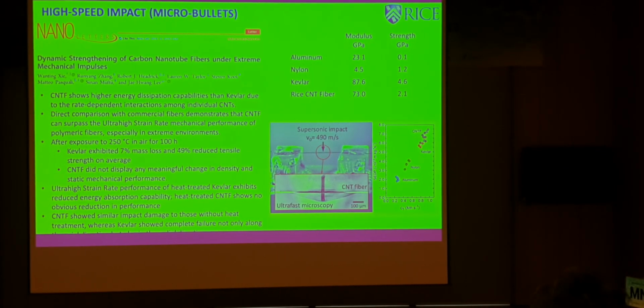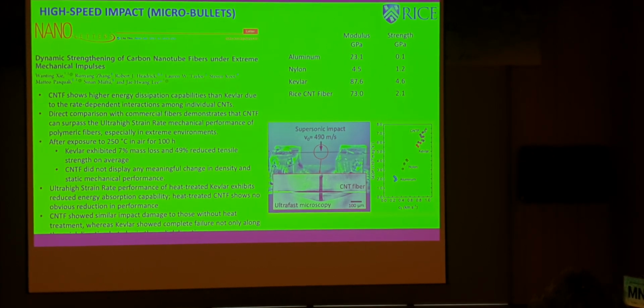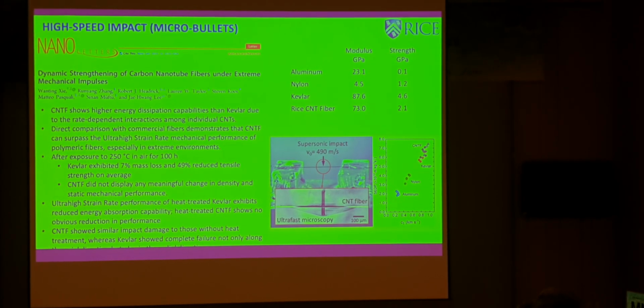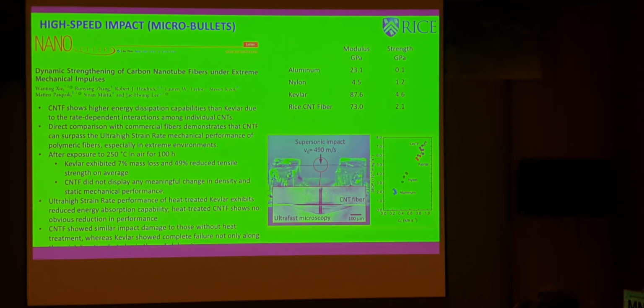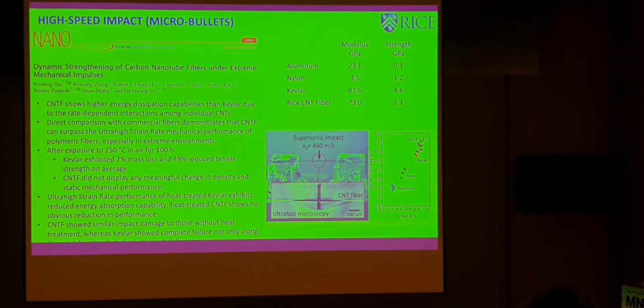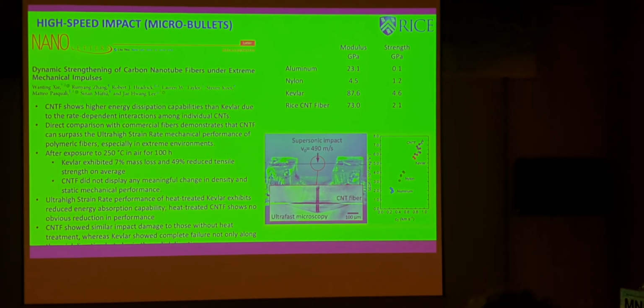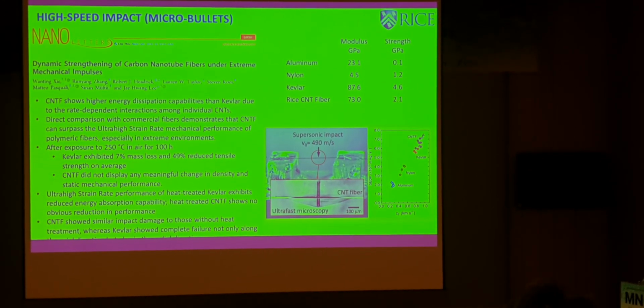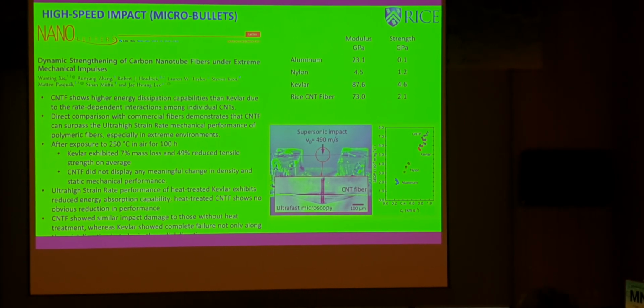Other things that were unexpected is high-speed impact. So this is a paper by Jae-Wang Lee at UMass. We collaborated, but we really just provided the fibers for this paper and helped a little bit with the interpretation. So what you see is that it took aluminum, Kevlar and nanotube fibers. And in this case, the nanotube fiber was significantly weaker than Kevlar. However, upon high impact, they behave better. And what was very interesting is when we got the result, I told Jae-Wang, send us back the fiber, we'll do Raman. And we did Raman at the end of impact. At the point of impact, we saw a lot of sp2 to sp3 transitions. So the D band was much higher, which meant that when the bullet hit, actually we broke covalent bonds, right? So that's actually something that was not expected.